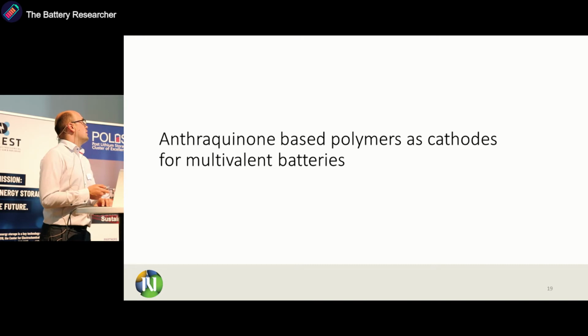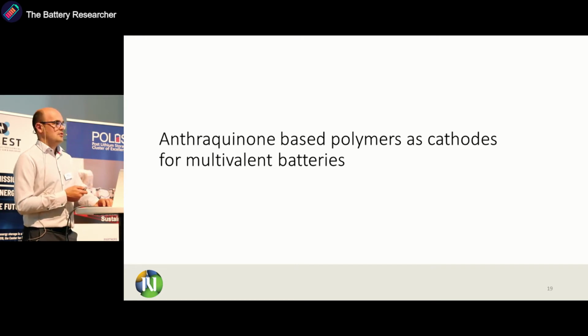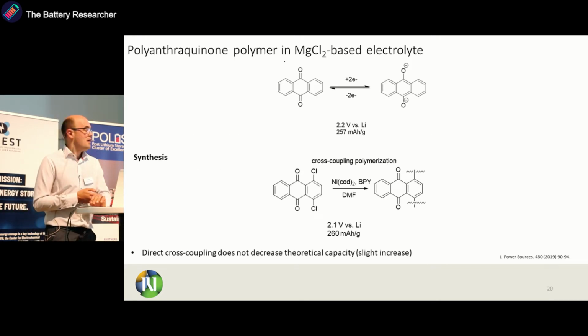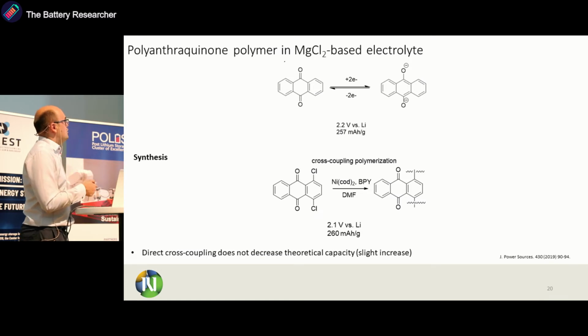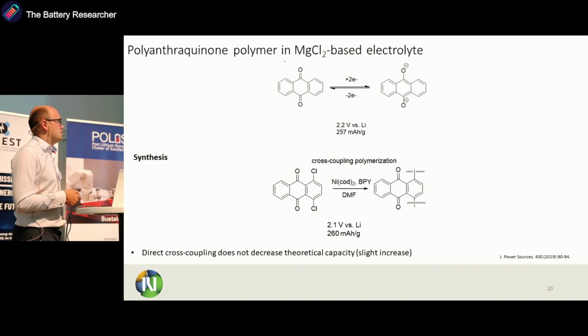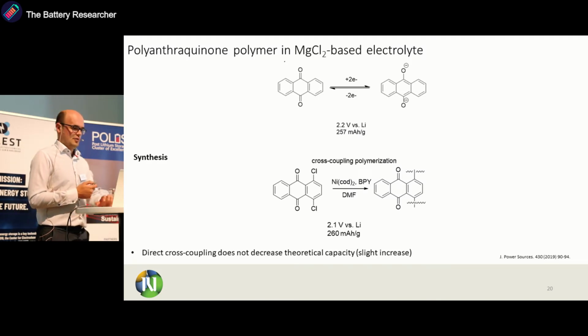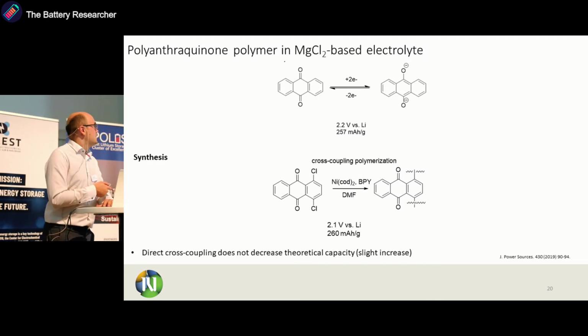And now let's move on to anthraquinone-based polymers as cathode for multivalent batteries. Anthraquinone is this organic group, which is quite known from organic chemistry. From many years ago, it was first used as a framework for making different colorants. And it has relatively moderate voltage potential, around 2.2 volts versus lithium, and capacity which is not extremely high, so 257 milliamp hours per gram. Like we said, this is quite soluble, so it's good to prepare polymers.